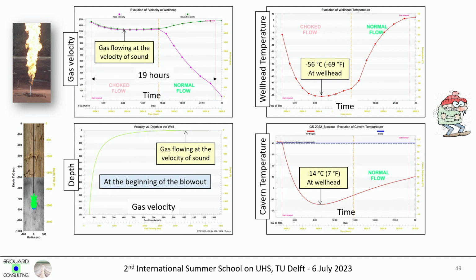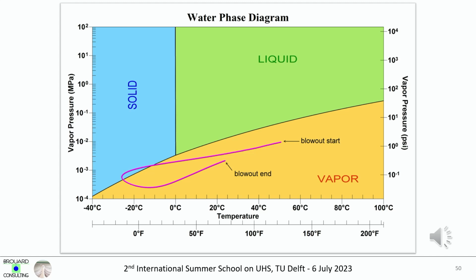This is an example of computation of a blowout from a nitrogen cavern. You have the gas velocity at the top left. I have no time, so look maybe on the right at the temperature. Top right, this is the temperature at the wellhead, and you can see that the minimum temperature you get at the wellhead is here, minus 56 Celsius, so it's extremely cold. And even in the cavern, you have a minimum of minus 14 at the bottom right here, and so you get some damage during the blowout because of the tensile stresses you create because of the large cooling of the nitrogen. And in some cases, because you are going very fast to low pressure and low temperature, you can go directly from a gaseous form of the water in the nitrogen directly to a solid form.